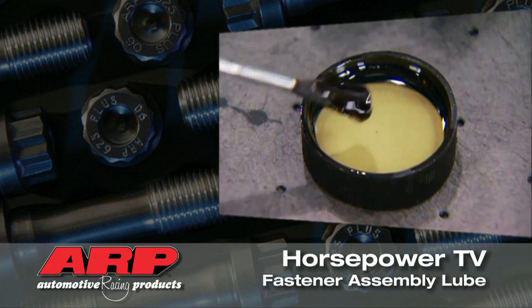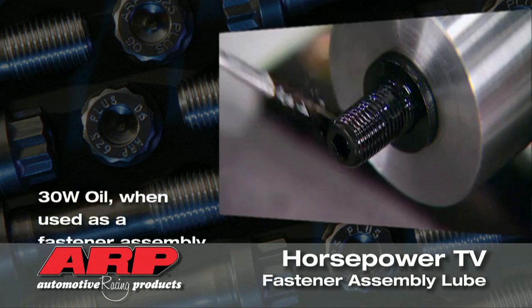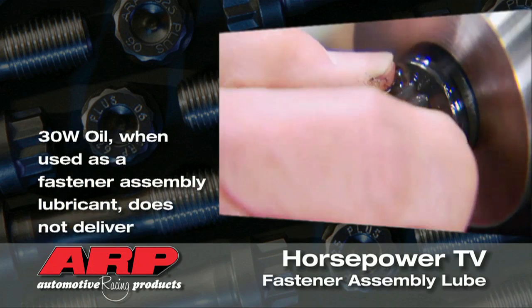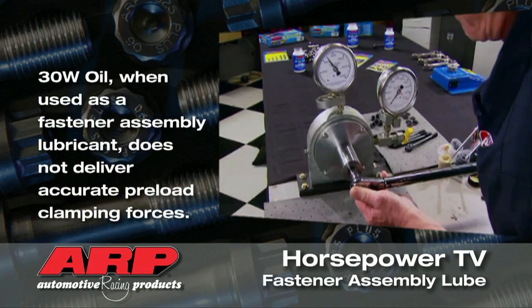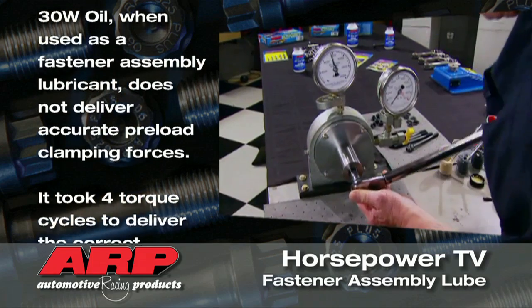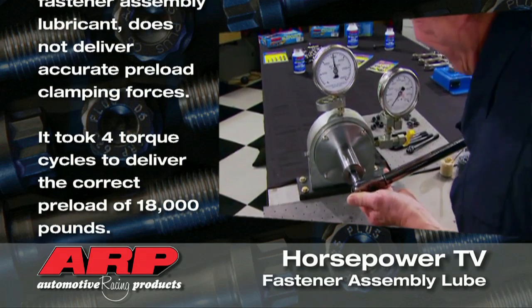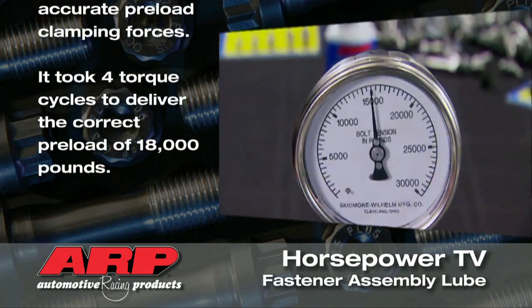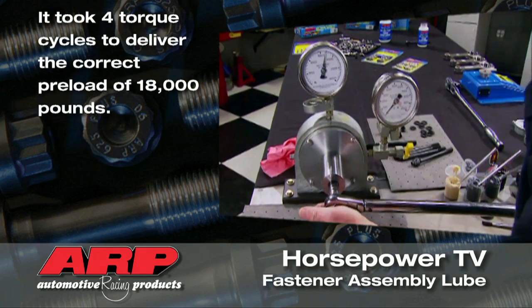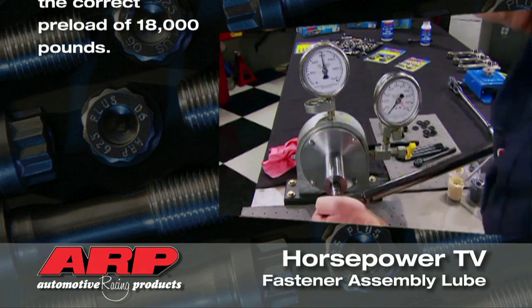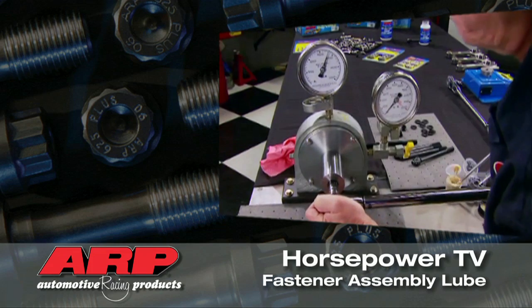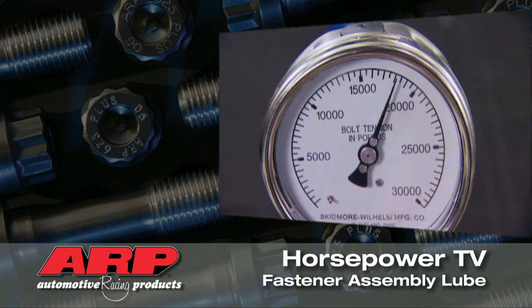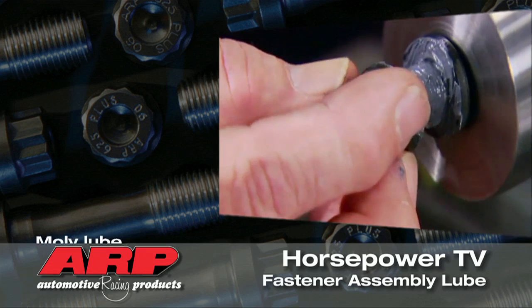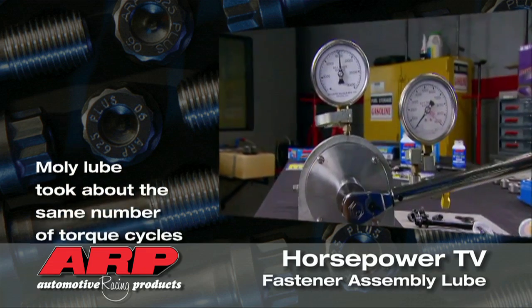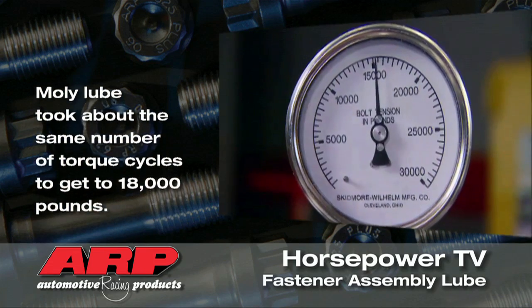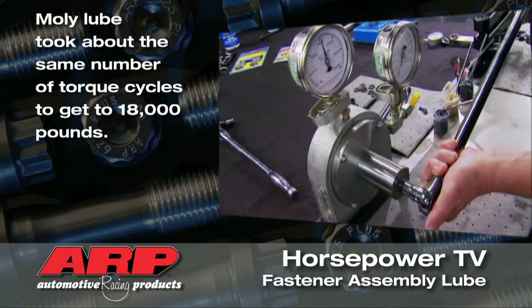First, good old motor oil on the threads of this ARP stud and nut, which has a torque value of 125 foot-pounds. So when the torque wrench clicks, the gauge needle should be at 18,000 pounds. And on the first cycle, we're at 15,000, not enough. And eventually we do hit the target, but only after several cycles. Next, with a new identical stud and nut, the ever-popular Moly lube. And once again, when the torque wrench says we're there, we're really 3,000 pounds under.